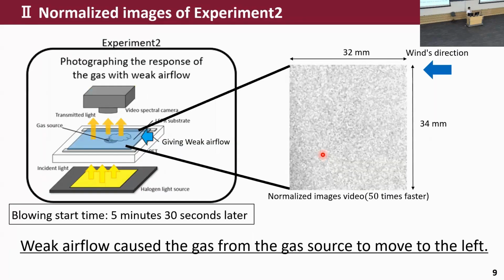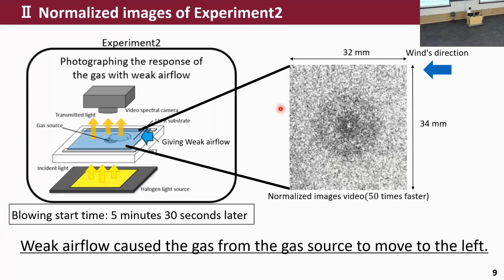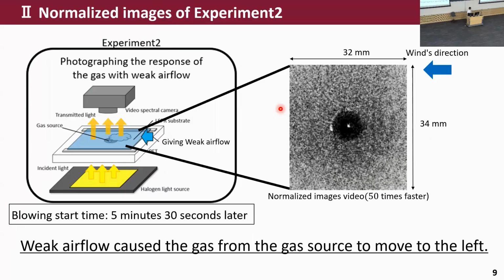The normalized images of experiment 2 are shown in the video. The gas spread, and with airflow applied starting at 5 minutes 30 seconds, we confirmed that the weak airflow caused the gas from the gas source to move to the left.